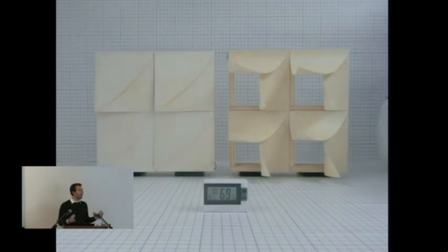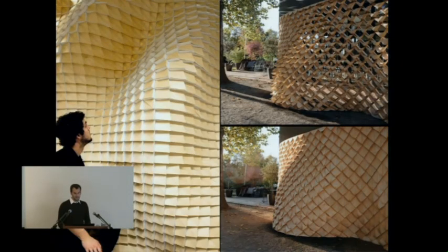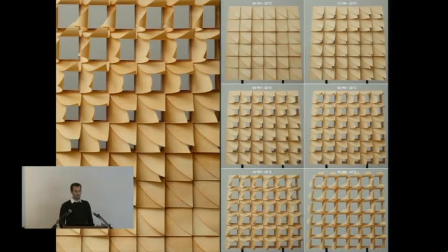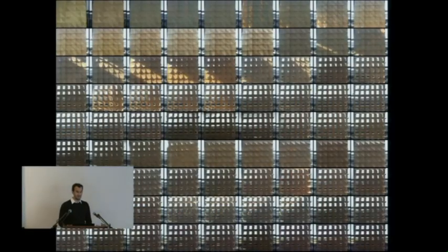And this doesn't entail any sort of electronics or other kind of technical gadgets. So we have tested this behavior in a number of full-scale functional mock-ups and verified the coherency and reliability of the movement in both laboratory tests and long-term tests in outdoor conditions, which we have conducted for over 1.5 years by now. So we monitor the system in environmental conditions every 15 minutes for more than 18 months now, and we can say that the system still performs absolutely faultlessly.